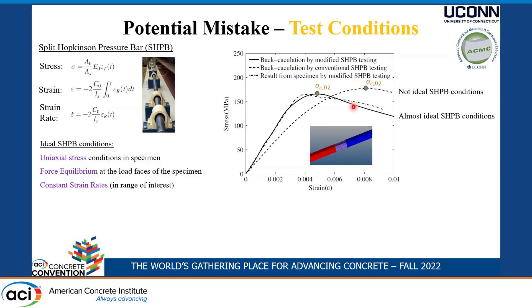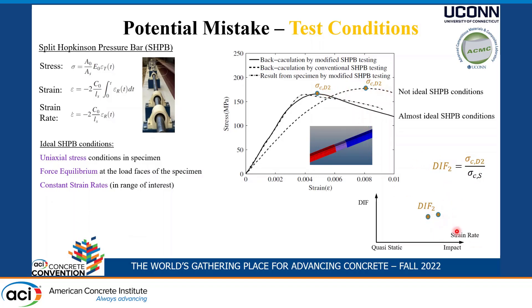Ideal conditions — even in finite element analysis — require pulse shaping, a constant strain rate, a certain specimen aspect ratio, and force equilibrium. Without pulse shaping in the finite element analysis, you get a different curve, and the DIF factor you calculate differs from the ideal curve. The associated strain rate also differs, so it is very important when testing or screening the literature to ensure those ideal conditions have been closely met.